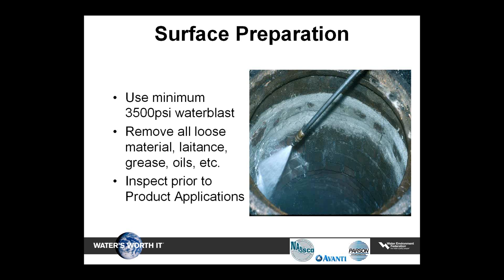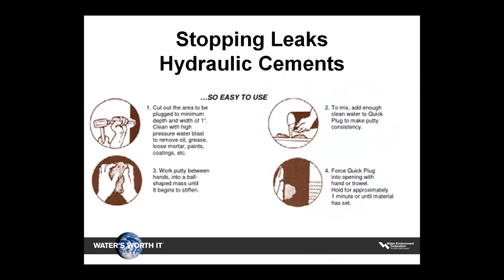A sand-assisted water blast at those pressures can be used if a more aggressive type of cleaning is needed. Care must be taken not to use excessive pressure, as that may cause unwanted damage to the manhole structure. Stopping active leaks is also a key element that will affect the bond of the lining product to the manhole. Cementitious lining materials are not designed to be applied where active leaks are visible. Their set times are too long for the products to have the ability to stop moving water. Use of fast-set hydraulic cements and urethane, acrylic, or acrylamide grouts is necessary to establish a leak-free manhole surface.